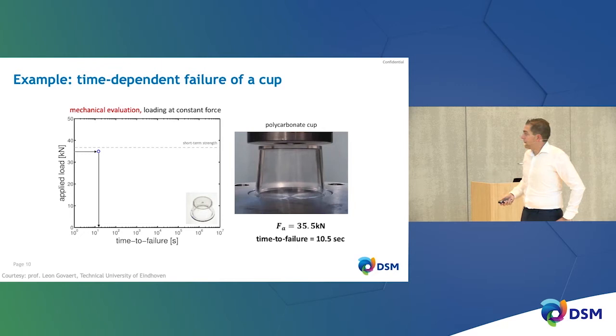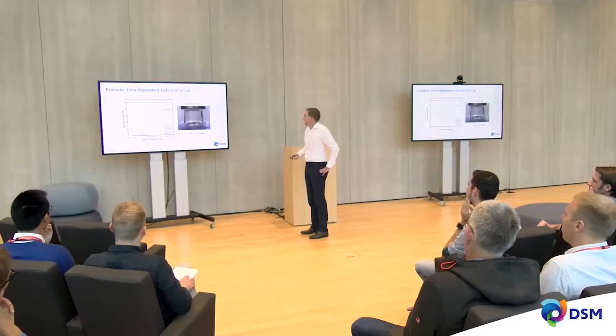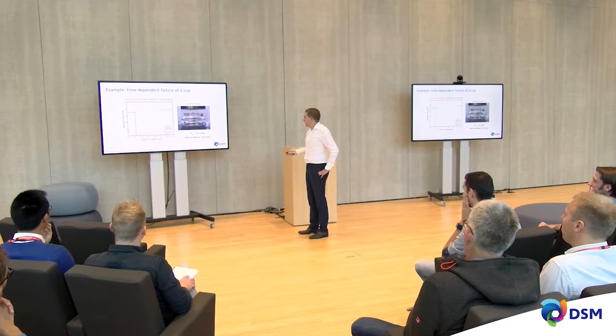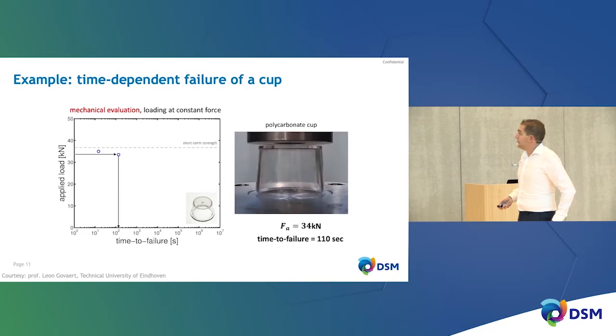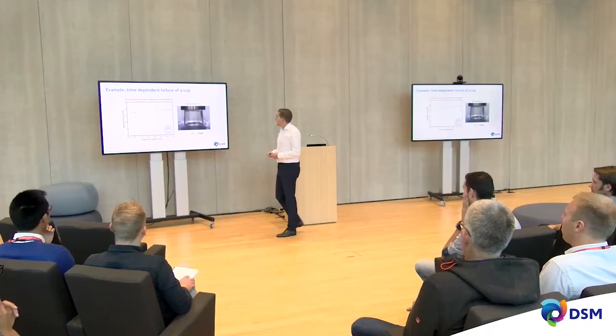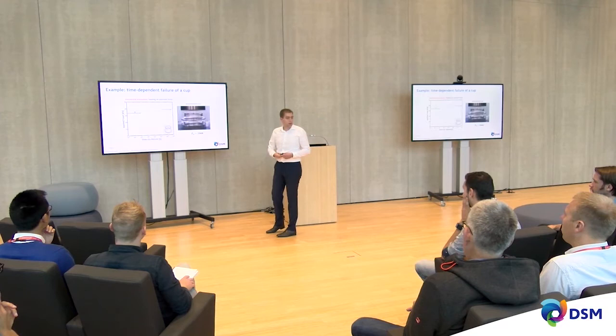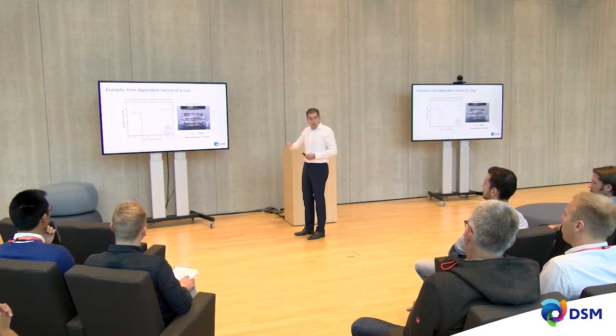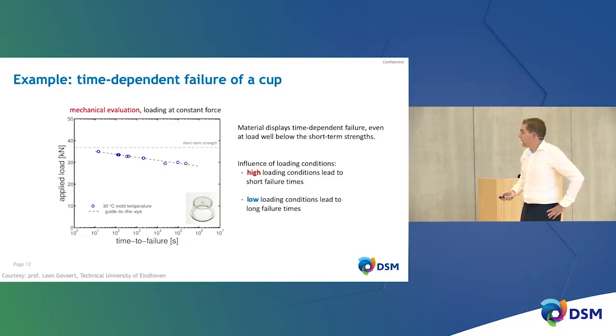To highlight this, I have an example from Eindhoven University where they loaded a polycarbonate cup with a static strength of approximately 37 kN. Loading it just slightly below that at 35.5 kN, you see a small elastic response, then gradual creep, then it starts to collapse — lifetime of 10 to 10.5 seconds. At even lower loads, still well below the short-term strength, you see similar behavior but with longer failure times — demonstrating clear time-dependent failure across many load levels.